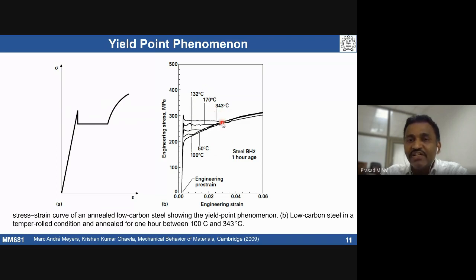With increasing aging temperature, what happens is reappearance of this yield point phenomenon. This is called aging—keeping the material at temperature and holding it for a while. If you then deform at room temperature again, we do see reappearance of this yield point phenomenon.